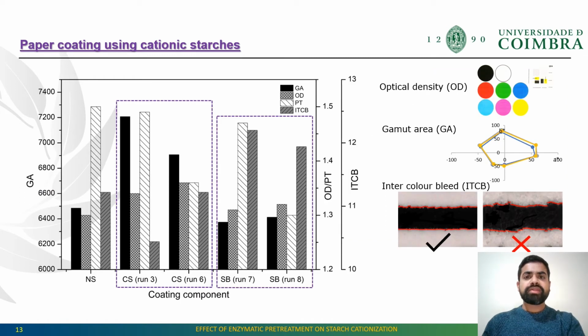As we can see in the graph, the gamut area increases along with the addition of cationic starch in the coating formulation. For the starch betainate coatings, it was observed that the gamut area remained in the same range as the native starch coating. The brown color of starch betainate in run 8 reduces the whiteness of coated papers, which significantly lowered the gamut area of surface coated papers. Unlike the starch betainates, the cationic starch ether coated paper showed an improvement in gamut area by 11% in run 3 and 6.5% in run 6, which may be due to the increase of surface positive charge of these coated papers.